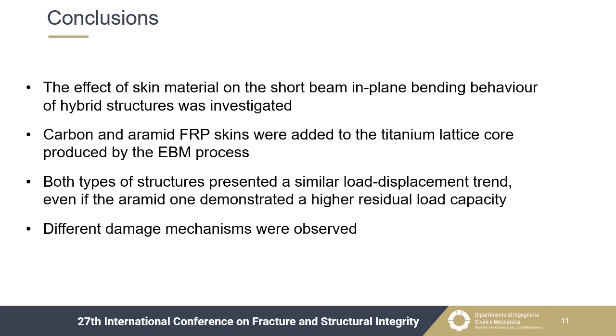The experimental tests evidenced very similar mechanical properties for CFRP and AFRP structures, with a similar load displacement trend, even if the aramid one demonstrated a higher residual load capacity. However, different damage mechanisms were observed for the tensile loaded fibers. The carbon fiber specimen presented a sharp fiber fracture, while for the aramid one, fraying was observed.